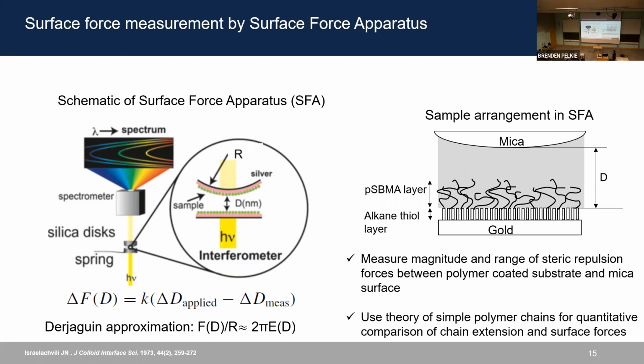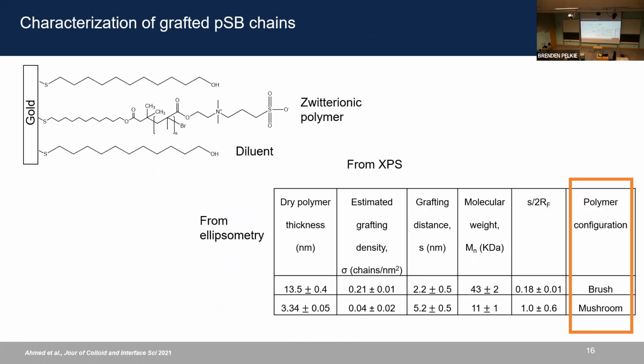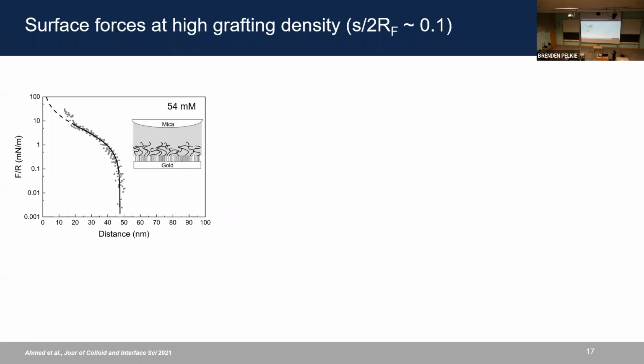So here, apart from measuring the magnitude and range of surface forces, we were also interested in quantitatively comparing the force distance curves at different ionic strength. And so we used a theory of simple polymer chains for quantitative comparison. So just briefly speaking, we worked with two different grafting densities of polymers, brush and mushroom-like polymer chains. And let's take a look at the surface forces at high grafting density, or brush-like polymer chains on the surface. On this graph, normalized surface force is plotted against separation distance. And we see that the onset of repulsion takes place around 50 nanometers, and it's a purely repulsive curve.